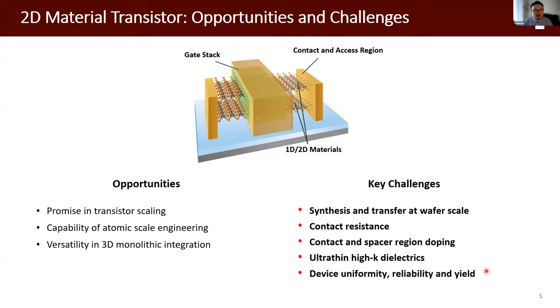There are also challenges to make this technology a reality. Here I listed some of the key challenges. The first one is how to synthesize and transfer 2D materials with high quality and at wafer scale. The second one is how to deal with the contact resistance issue when we contact this 2D semiconductor with the metal electrodes. The third one is how we can design an effective and stable chemical doping method to dope the contact and the spacer region of the transistor. Then we also need to develop a high-k dielectric technology to interface with the 2D semiconductors so the gate control can be perfectly as designed. Lastly, we also need to deal with different non-ideal factors like device uniformity, reliability, and yield.